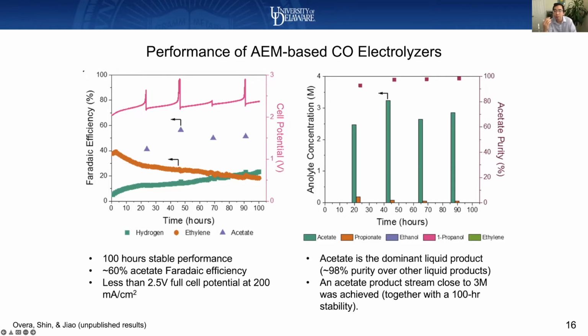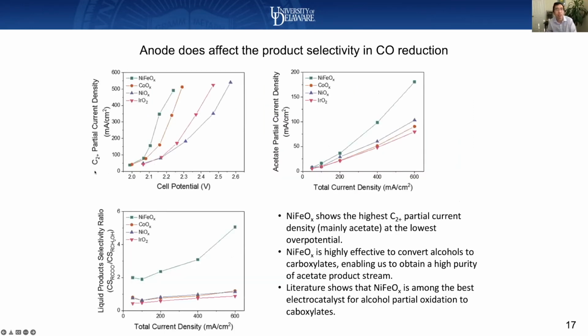First, we thought maybe there's some difference in terms of the reaction mechanism when we use different catalysts, but we ruled it out because we're just using a very common copper catalyst. And later on, we found the disappearance of alcohols, and why it becomes acetate and propionate, is actually due to this partial oxidation of alcohol at the anode. So we try to go one step deeper into this and try to prove it.